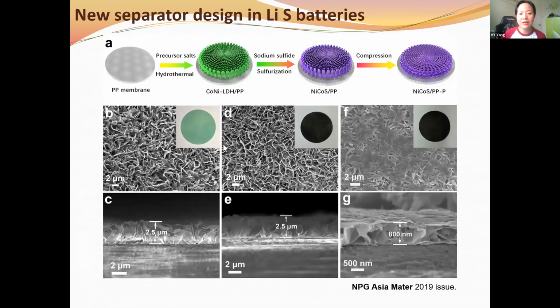We have also generated a PP membrane decorated with nickel cobalt sulfur, which prevents the soluble lithium polysulfide from going through from one end to another. That further confines the generated lithium polysulfide to be trapped inside one terminal, for example the cathode terminal, and it won't go through to the anode terminal, preventing further dissolution of this long-chain polysulfide.